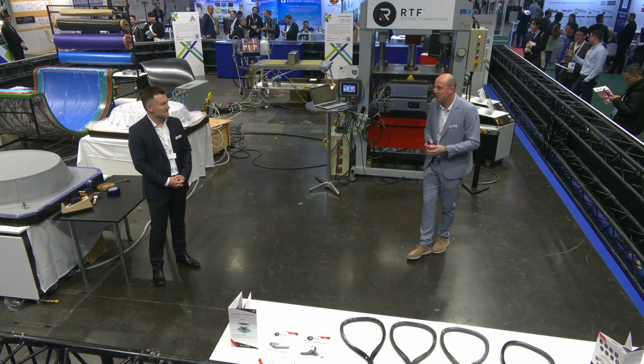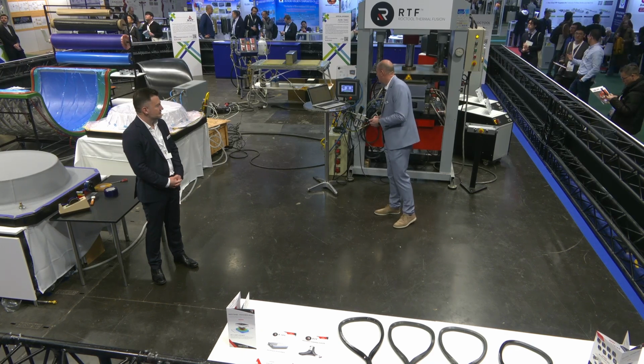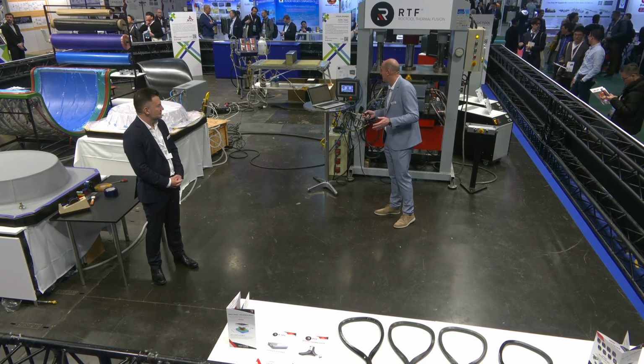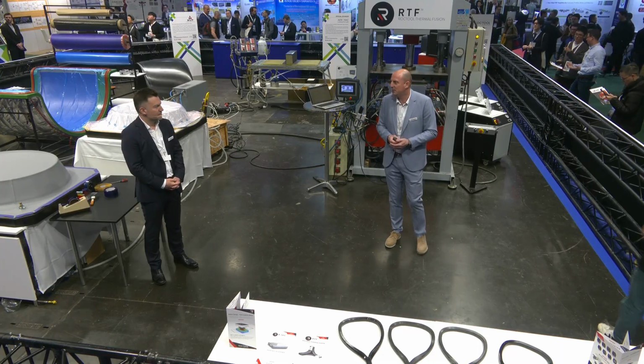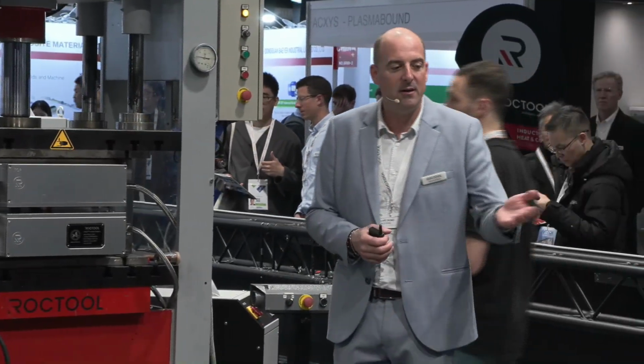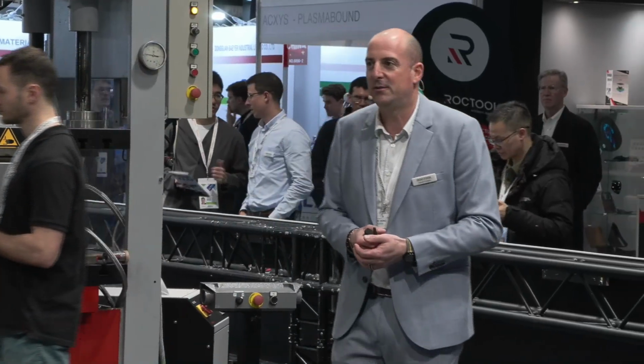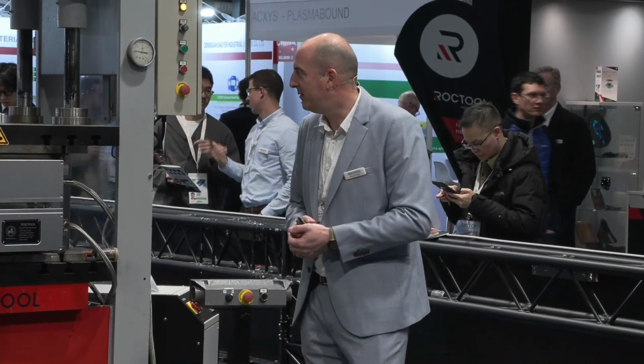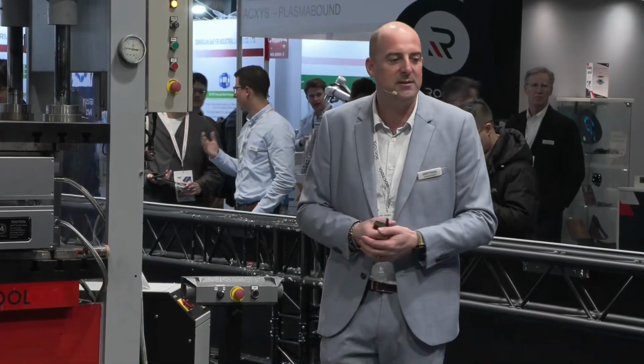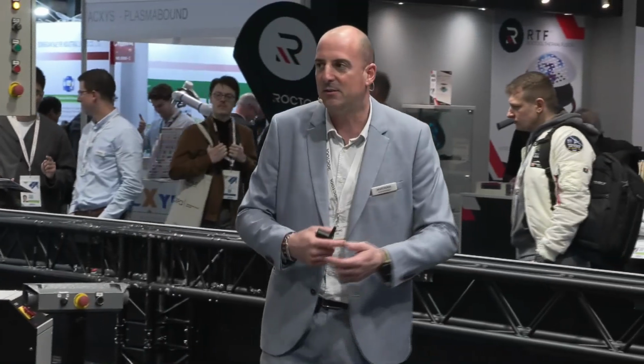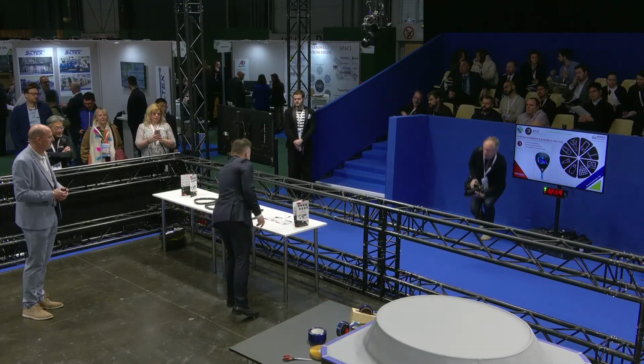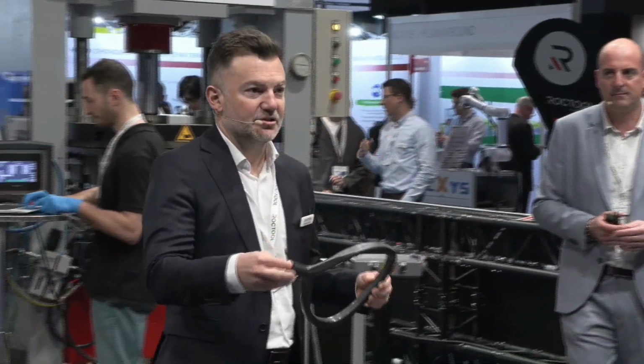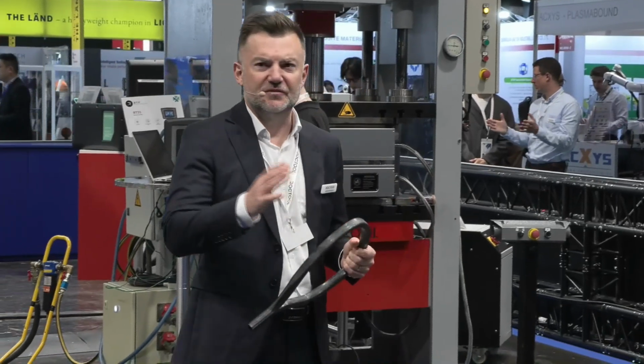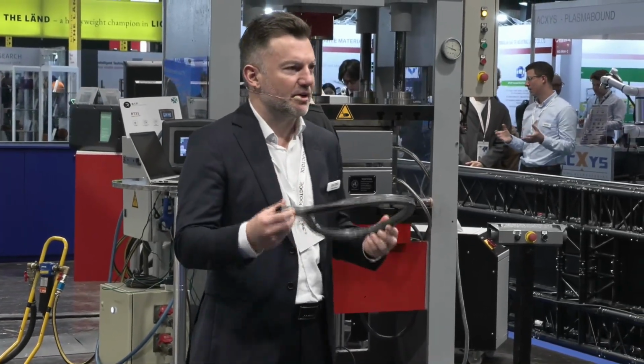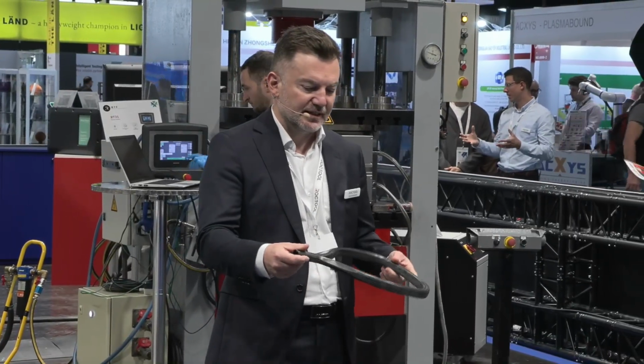So now we have quite finished the cycle. Again, a few seconds before the demolding temperature. As you see, in less than 12 minutes, maybe, we are able to manufacture this example of a racket paddle frame. And in a few seconds, we can open the press, demold the part and restart a new cycle easily. Exactly. Typically on this component, with the silicone bladder, we can have the inner structure, and it also gives you up to 15 bars of internal pressure, which is required for a good consolidation.